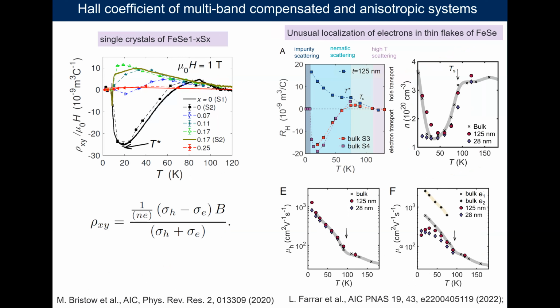Next is the Hall effect, the Hall coefficient. It's been used a lot in cuprates to justify changes in Fermi surface reconstruction and other effects. Now, in a multiband system, if the system is very well compensated, we should expect that the Hall coefficient should be zero. So at high temperature, indeed, we find that the Hall coefficient is zero. Now, when we reach the nematic phase for iron selenium, suddenly the Hall coefficient becomes strongly negative. And it's as if the system loses carriers. But obviously, we have already seen that the Fermi surface is only distorted. So how is it possible for the system to lose its carriers?